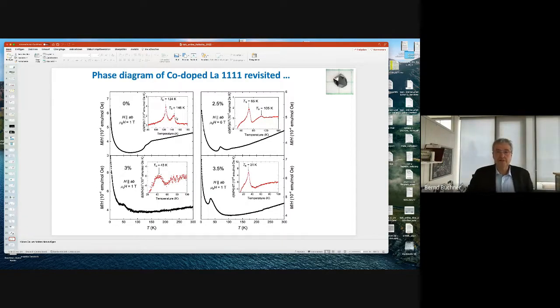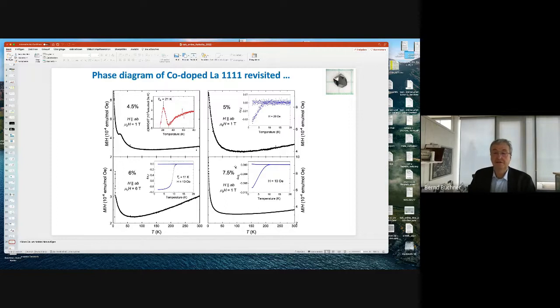Where you see both transition first at small doping, and then you can follow these phase transitions. I will not go into details because we are already running out of time. This becomes superconducting later on at 6%. Reasonable superconductor, but Tc is much smaller. That's what we expected due to these cobalt impurities.